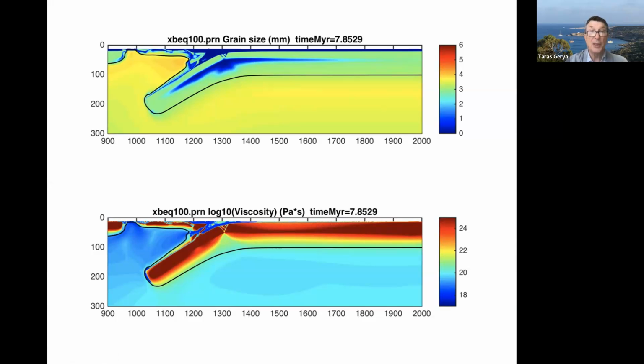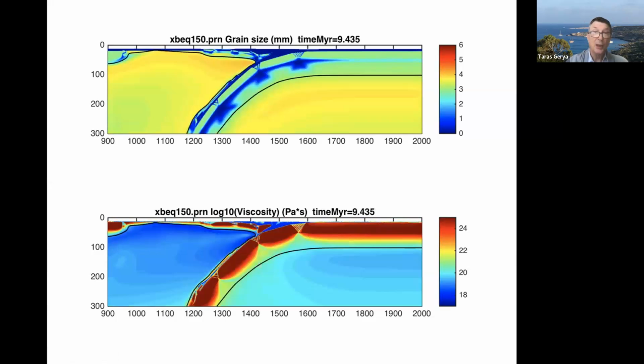So as a result, we have this segment boundary formed, and then the next boundary only forms after a significant amount of the slab has already subducted. So you need to subduct some critical length to start forming the next segment boundary. And the mechanics and the physics of this process is always the same. We have focusing of brittle deformation due to the fault weakening, and then the slave process is this grain size reduction, which is responding to brittle localization, and then produces these nicely formed triangular segment boundaries.